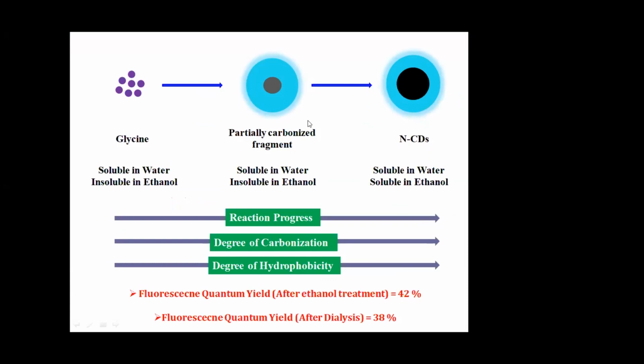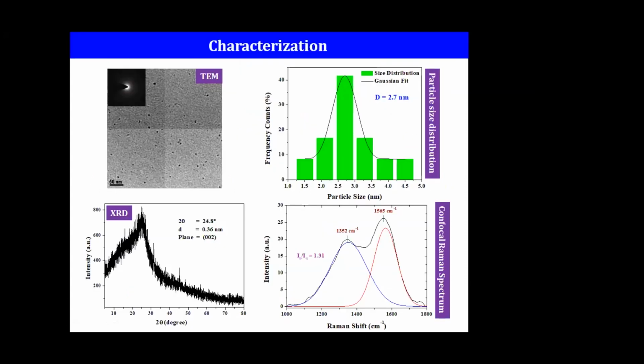Now you can really see the quantum efficiency of this material is different and a little higher. You can see what is enhanced after dialysis. We have also done the dialysis as a reference to see what kind of quantum efficiency we get. We can go for an ethanol treatment, which itself gives a better material, with a quantum efficiency of 42%. Compared to this, dialysis basically removes the unwanted organic material. We always make it as a reference to compare and use this material for the application.